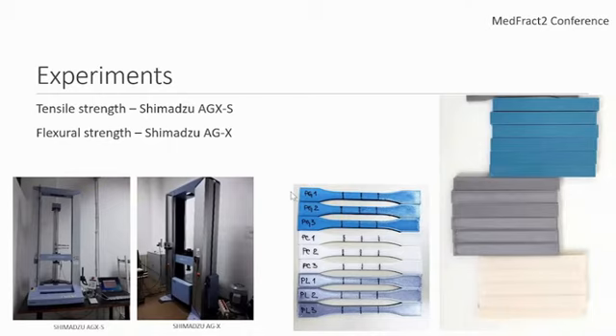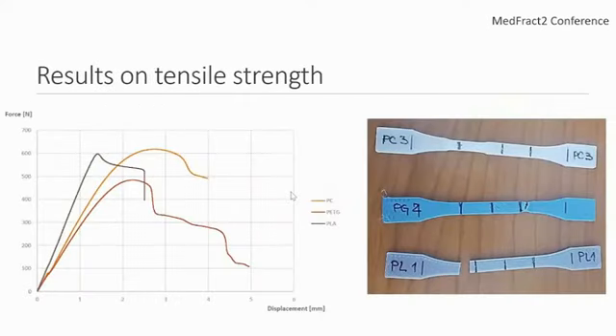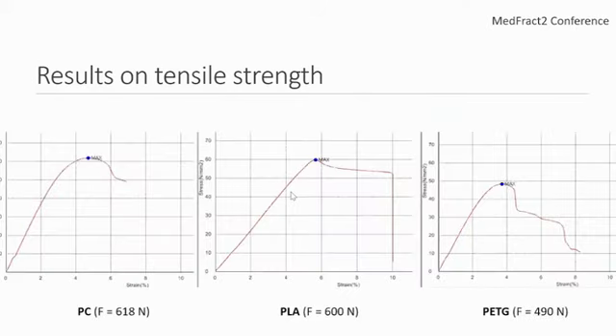On the slide, you can see the samples that we used for the experiments, and on this slide you can see the results from the tensile strength. The results are as we expected. As you can see on the probes, the PLA is completely broken. The PETG material showed some stringing, and the polycarbonate shows plastic deformation and showed the most elasticity. On this slide, we are presenting the tensile strength of all three different materials. As you can see, the PETG has the least force.